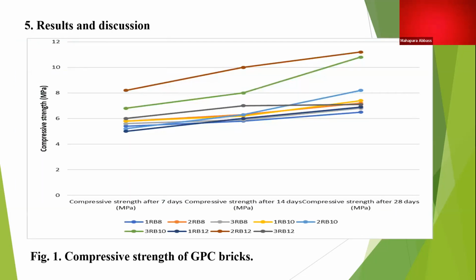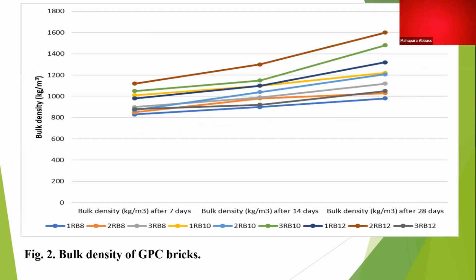Coming to the results and discussion, we found that 2Rb12, which means silica to alumina ratio of 2 in the rice husk ash and alumina based bricks and with sodium hydroxide molarity of 12, got the highest compressive strength for 7, 14, and 28 days. The 28-day strength was more than 11 MPa for the rice husk ash based brick. The same happened with the bulk density. The bulk density was also maximum for 2Rb12, for which the silica to alumina ratio was kept as 2 and sodium hydroxide molarity was kept as 12.